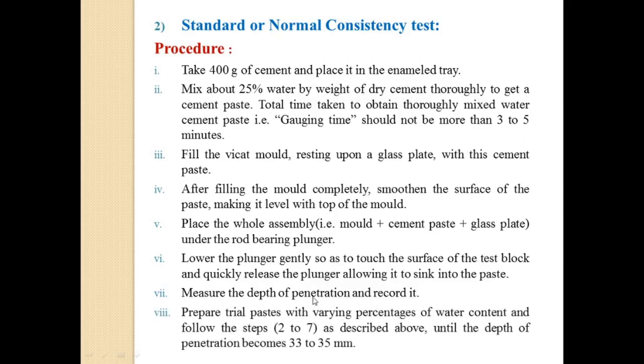number of trials. So prepare the trial paste with varying percentages of water content, and we have to follow steps number 2 to 7 again, until the depth of penetration becomes 33 to 35 mm. So firstly, suppose we add 25% water.